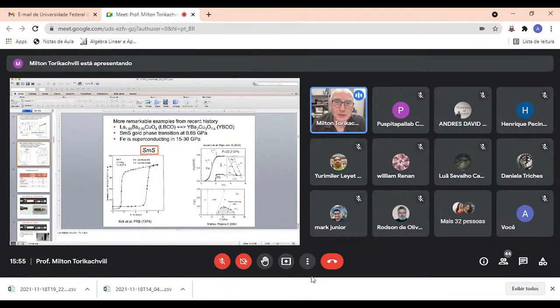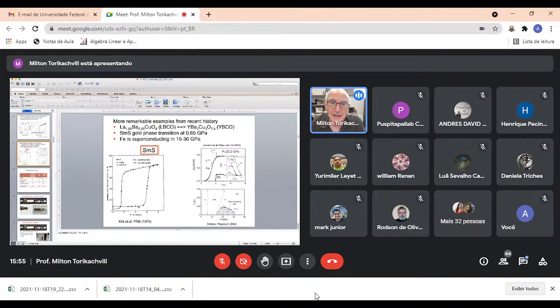Okay, I told you a little bit about samarium sulfide before. On this plot on the left, we have the normalized reflectivity versus pressure. So you see at the low pressure, the normalized reflectivity is very small. Okay, the thing is not conducting. But as you apply pressure, the reflectivity keeps growing. Okay, and you reach 80% at a pressure of 6 kilobars.